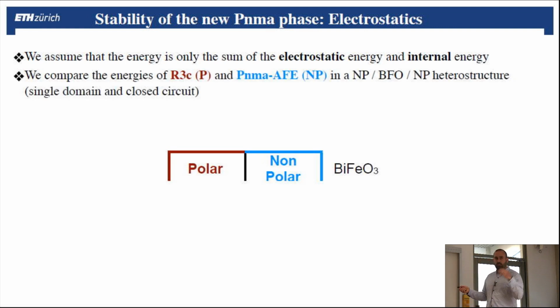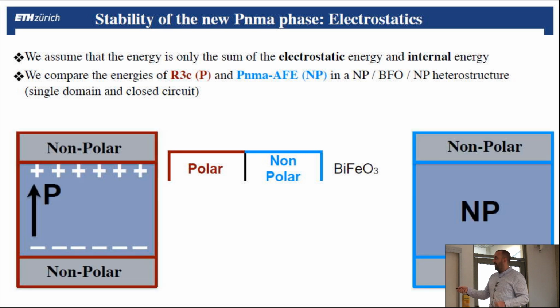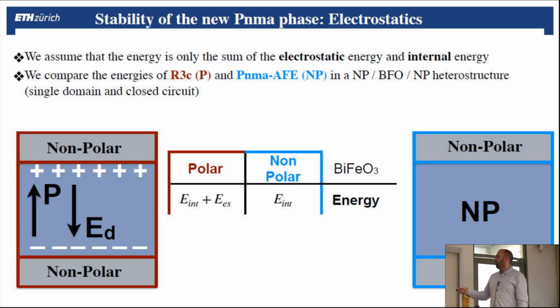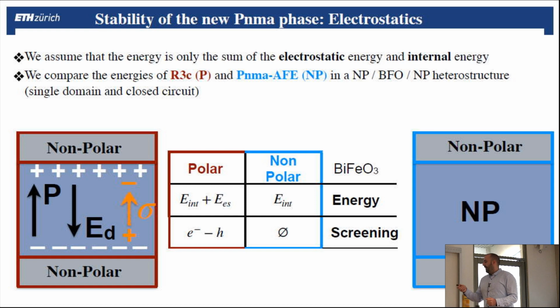And we consider now the R3C phase, which is the polar ground state, with the lowest non-polar phase, which is the one we identified. And again, we assume that we have non-polar material surrounding bismuth ferrite, and the same here. So for the polar case, you will have polar material, non-polar, discontinuity, accumulation of charges as we saw before. If the material goes to a non-polar phase, everything is non-polar, no problem. In terms of energy, that means that now we can say that here in this case there is the internal energy and there is this electrostatic energy also. In that case, there is only the internal energy.